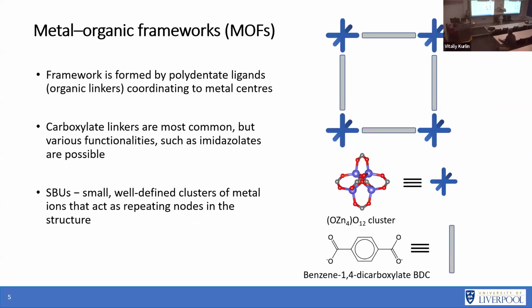So MOFs can also be represented like this. This is just another representation. You've got this framework formed by these polydentate ligands or organic linkers coordinated to these metal centers. This is a bit of a simplistic view of these materials, but it's just to show you the general representation of how you'd make up a metal organic framework. The linkers that we're talking about are typically carboxylate linkers. It's definitely not just carboxylate linkers that we use to make these frameworks. Carboxylate linkers are these linkers here with these carboxylates on the end. You can also have imidazolates, bipyridyls, pyridyls, etc. So there's an endless number of linkers that you can use to make these kinds of frameworks.